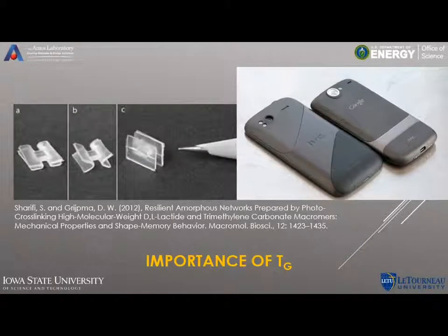Now, you've heard glass transition temperature mentioned multiple times here in the course of the presentation. And that may be a slightly unfamiliar term, but it's very useful and important when looking at polymers. Here's some research on the left-hand side where you can see plastic components developed, say for a medical implant. And those have a glass transition temperature right about at body temperature. And so you could heat them to have them collapse and then insert them during surgery, and then they would expand again into rigid form to take on their function as a medical implant.